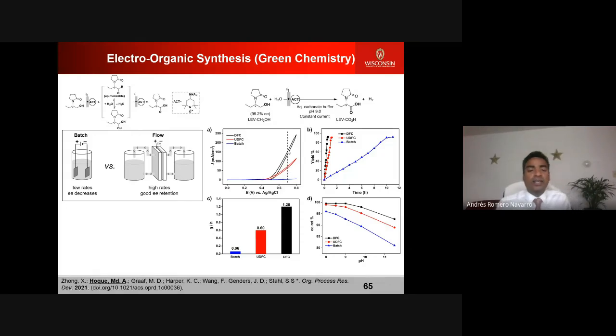But the black one is showing that when we have this divided cell, we are even improving the kinetics and getting a faster reaction. And that is already reflected when we calculate the yield. We apply the potential or current here, and we wanted to see the formation of the product. What we found, as I'm showing in panel B, is the yield versus time. In the batch, to do this transformation for a particular scale, it takes more than 11 hours. But when we do the same reaction in the divided cell, it finishes in less than 30 minutes. So the flow process is so efficient.